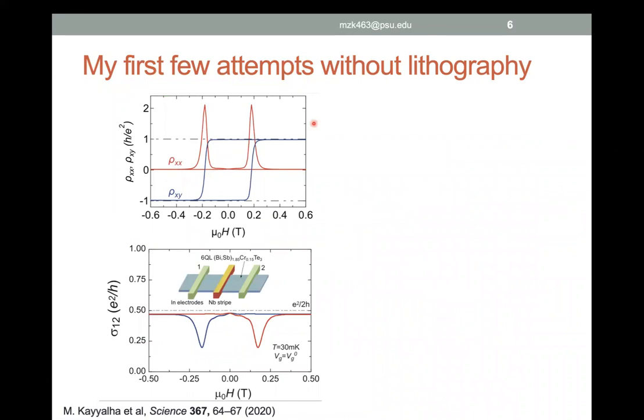So in my early attempts, I didn't want to use any lithography because the experimental report in that paper seemed to be actually done on millimeter size samples. So there is no lithography needed. So I got a bunch of quantum anomalous samples. This is basically 6 quintuple layer chromium doped bismuth antimony telluride samples.